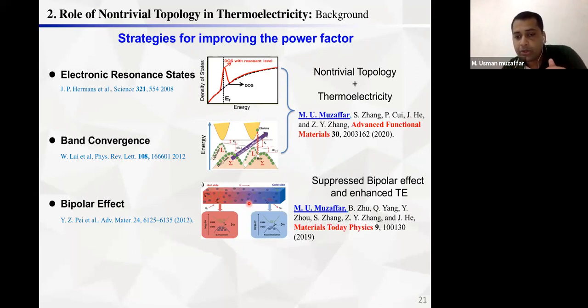So to get high efficiency, a high Seebeck coefficient, we need to enlarge the band gap, so that at high temperature, only the majority carriers can take part in the conduction, and we can get a high ZT. As I mentioned in the starting slides on the ZT of thermoelectrics, electrical conductivity is directly proportional to the ZT. ZT is the efficiency. And topological insulators have a high electrical conductivity. So it should be expected that the efficiency of the thermoelectric material should be high.